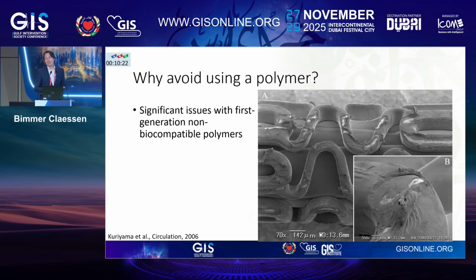Well, there were some significant issues with the first generation non-biocompatible polymers on the Cypher and Taxus stents. And this is a scanning electron microscope picture of a Cypher stent that they tried to implant in a patient through a previously placed stent. They weren't able to get it past the stent, then they took it out and they put it under a microscope, and this is what you see. Lots of irregularities in the polymer. This can lead to delayed tissue coverage of the stent struts, which can then lead to a prothrombotic environment, and which can lead to stent thrombosis.